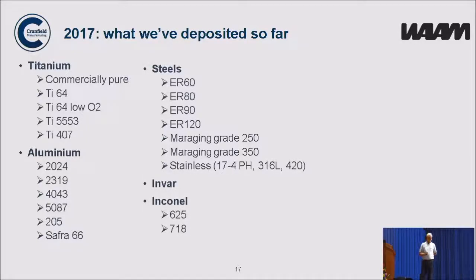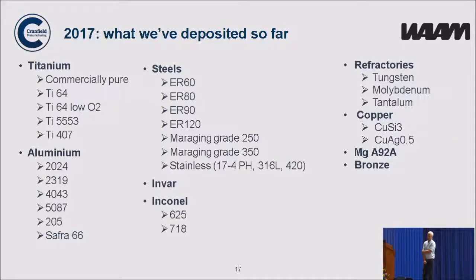In terms of steels, these are mainly for the oil and gas sector, and we've looked at ER 60, 70 as well actually, 80, 90, 120, different kinds of maraging steel and also stainless steels. We've done Invar and the primary Inconel alloys of 625 and 718. As well as these primary structural materials, we've also looked at different kinds of special metals, if you like. The refractory metals tungsten, molybdenum and tantalum, and then some copper and magnesium and bronze. And really there's no particular reason why you can't do any materials, as long as you can get the wire.